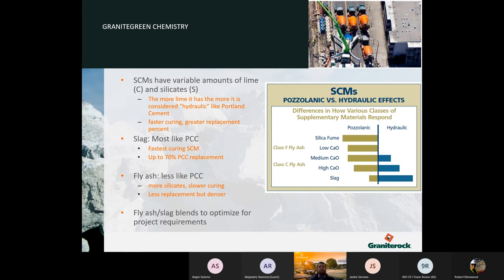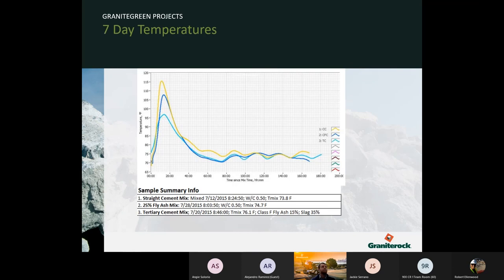Fly ash is less like Portland cement, so it has more silicates, slower curing and less replacement, but it does create a denser mix. Really, you can blend all three and they can be optimized for each project.